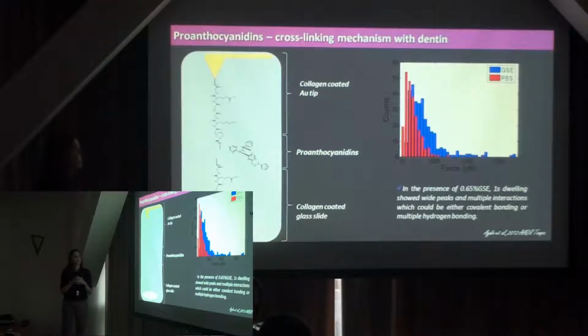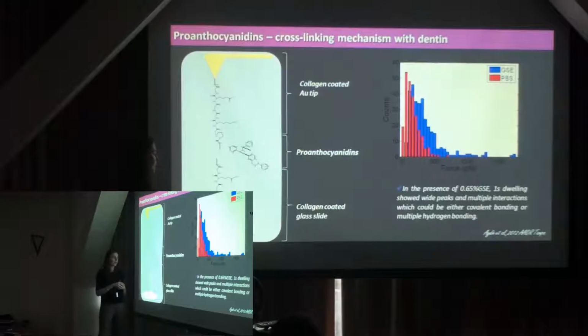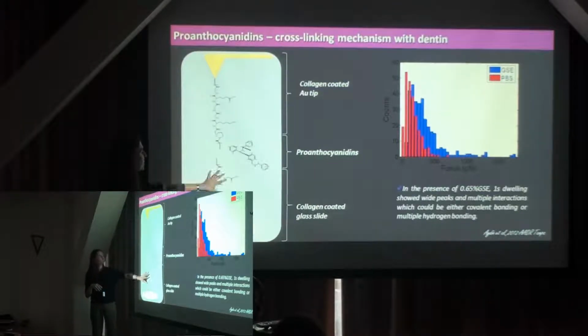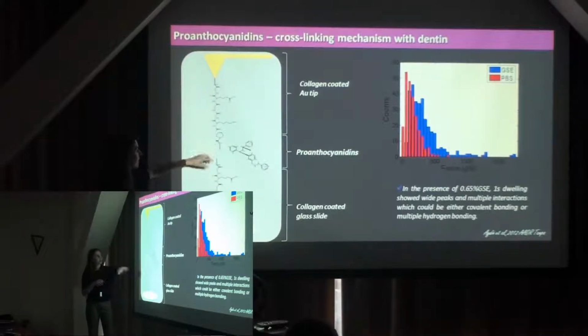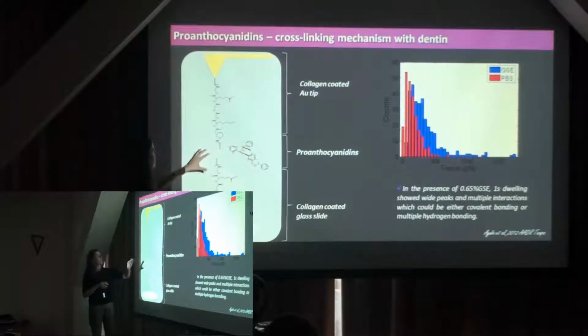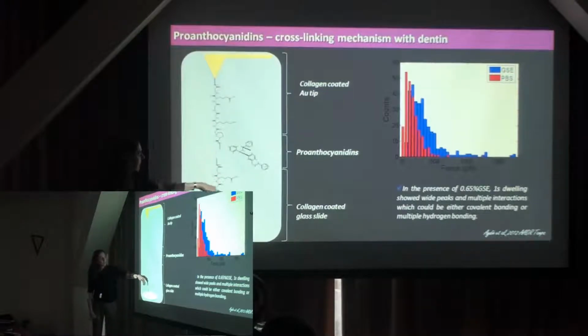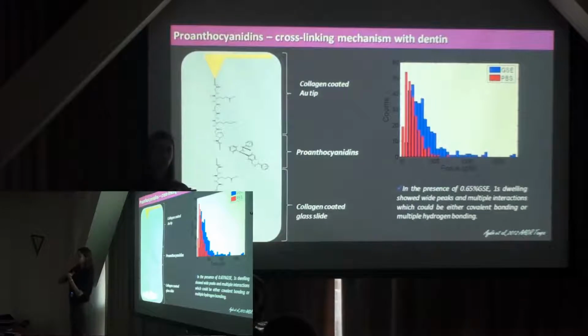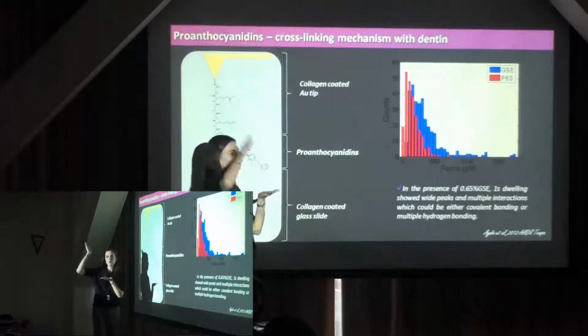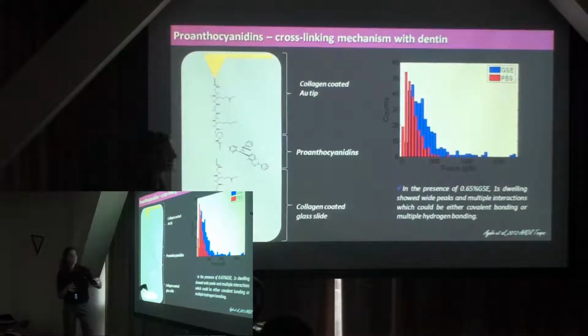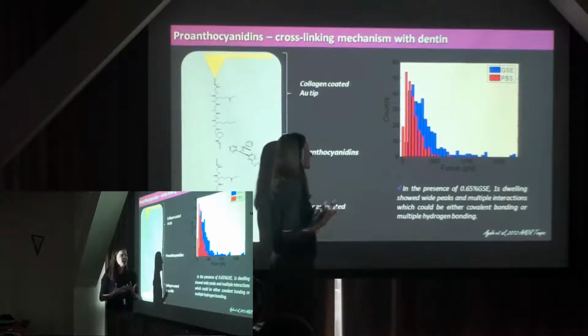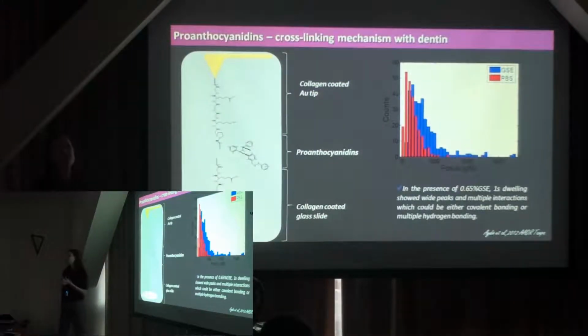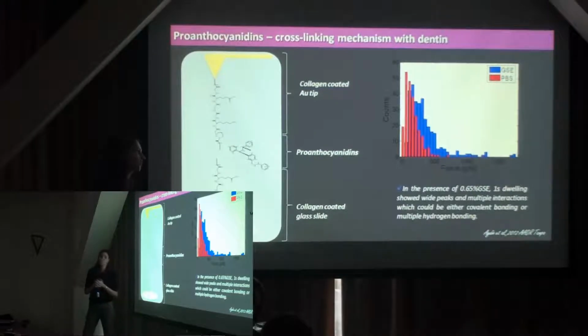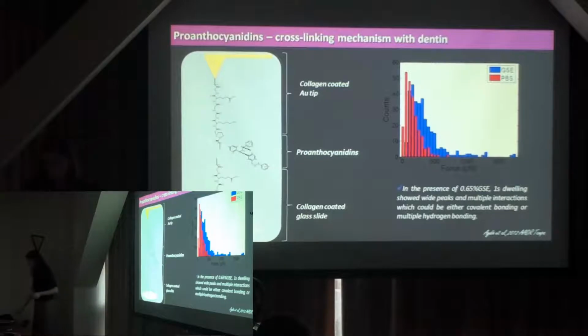So this was one assay that we used to try to understand how this works. We used collagen-coated glass surfaces with soluble type 1 collagen. We coated tips of AFM with the soluble collagen, and we introduced in a fluid medium, PBS, these proanthocyanidins, and we got the tip of the AFM to get in contact with the surface, and we measured the retraction force, how much it would take for us to pull it from the surface, like you have a fishing pole. What we saw is an intense increase in retraction forces, which indicated that we have either covalent bonds or a lot of hydrogen bonds. So this has been sort of an indirect method for us to try to quantify the chemistry of how they bond to collagen molecules.